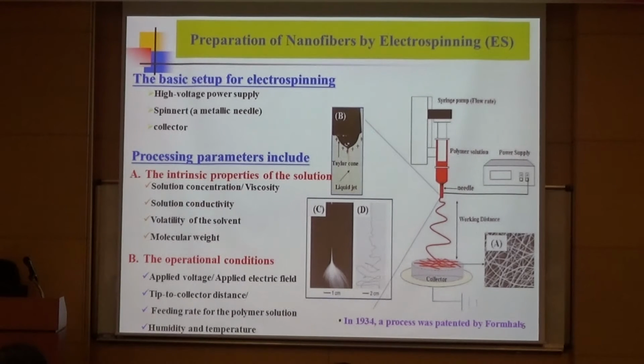So the electrospinning technique is a popular way for fabrication of polymeric nanofibers with diameters in the range of several hundred nanometers. The basic setup for electrospinning is composed of a high voltage power supply, a spinneret, and a collector. As the syringe pump pushes the polymer solution through the spinneret, the electric field between spinneret and the collector will overcome the cohesive force of polymer solution and result in the formation of a fibrous structure. And then the nanofiber will be collected on the collector. So the morphology of a nanofiber could be manipulated through the controlling of processing parameters in 2 major categories: the intrinsic property of polymer solution and the operational conditions.